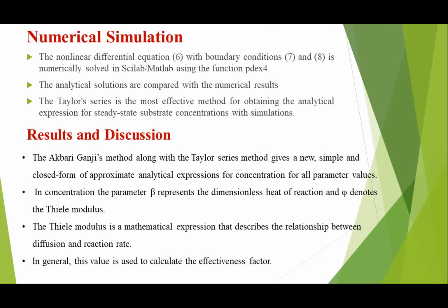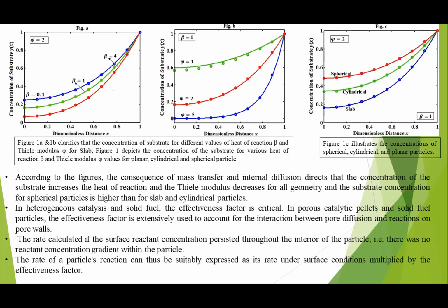Now let us see the diagrammatic representation of the concentration of substrate versus dimensionless distance x. When beta is varied over 0.1 to 1 as well as 4, when the Thiele modulus is equal to 2, the first figure is obtained. And when we change the parameter beta to 1, then the second figure is obtained like this. And when we vary spherical, cylindrical, and slab, that is the planar coordinates, for phi equal to 2, then the concentration of the particles is illustrated here.